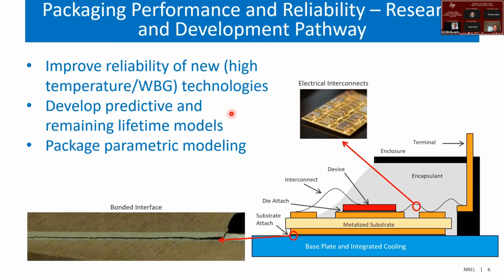We've been working along with collaborators on improving the reliability of each of these technologies, developing predictive and remaining lifetime models. And that's specific to a failure mode. I'm showing a bonded interface here, and this is a cohesive fracture that is happening. That's what can happen under some of the thermal cycling and the stresses. But the lifetime models, predictive models, are specific to the failure mode. We also want to identify processes which help improve the lifetime of these components or subcomponents.